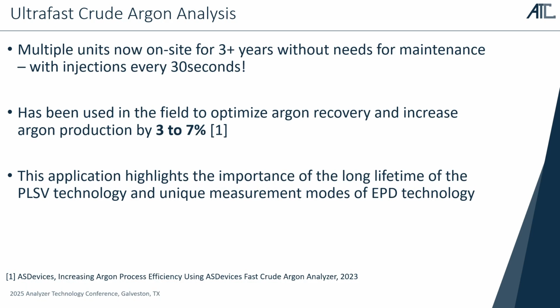And also, again, this result highlights the importance of the valve that was used, because we now have multiple units on site that have been used for over 3 years with injection every 30 seconds without need of maintenance for the valve. And since we were able to do this test, people who implemented this system have been able to improve their argon recovery by 3 to 7%, which is very interesting considering the cost of argon on the market at the moment.